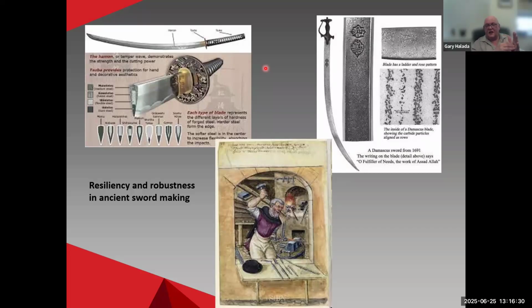interfaces. The same thing can be said of other metals that have been very famous for their use in swords, for example, Damascus steel, more properly called wootz steel. In the upper right here, you see these swords that were made in the East, originally developed in India, which had a microstructure that included lines of carbide particles. Those carbide particle patterns, which could be quite beautiful on the surface of the steel, were formed due to adding phosphate to the steel. And actually, the phosphate and calcium that enable these small particles to form came from putting bones into the furnaces, so that you would add those materials to the metal. It was kind of considered magical at the time, but we now know how it works. Again, a crack, which is a defect, hits particles and gets stuck, and so it becomes a more robust material.